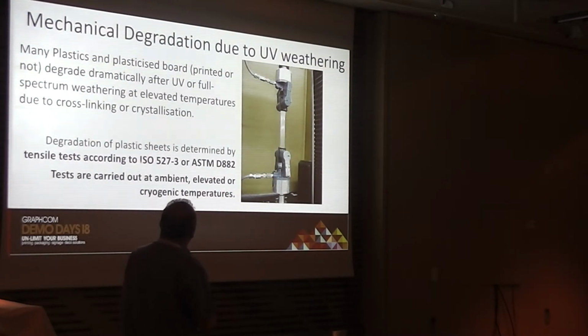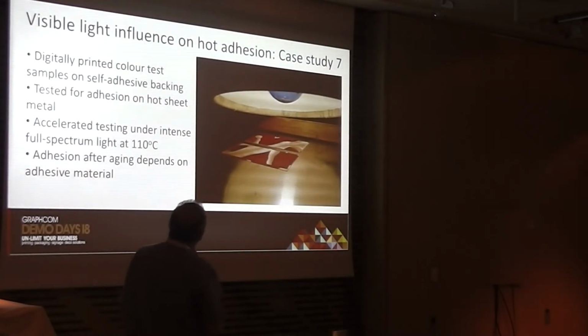Lots of things. We can go down to ambient, we can go up to 250 degrees. Okay, you never see that, but you do get some machinery that works in high temperatures. So we are asked to do some testing because the metallic surface is actually very hot. And we can go down to very low temperatures, down to liquid nitrogen, you don't need it, but you can go down to -20, -30, -50.